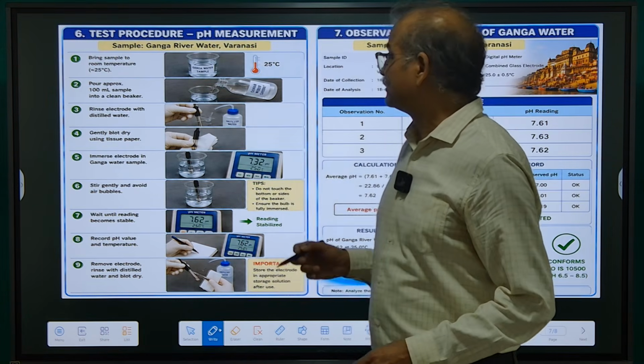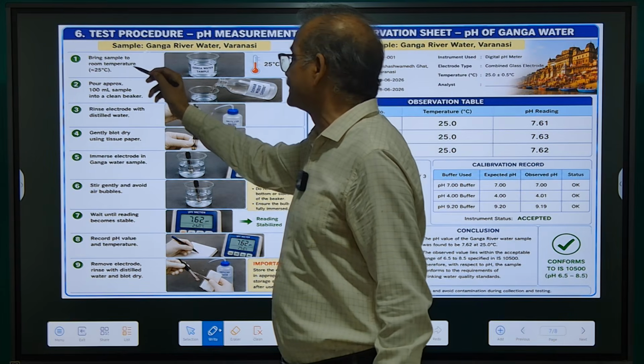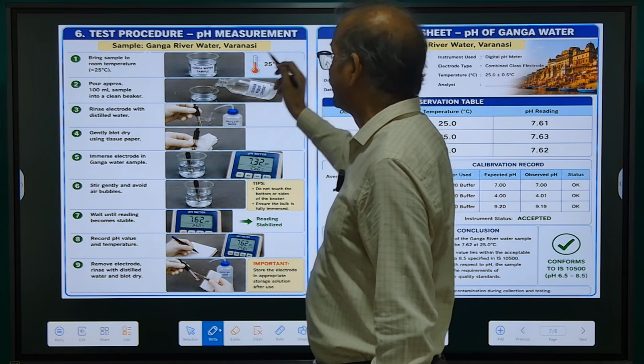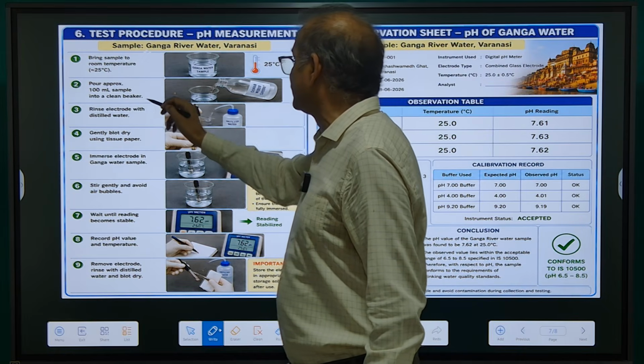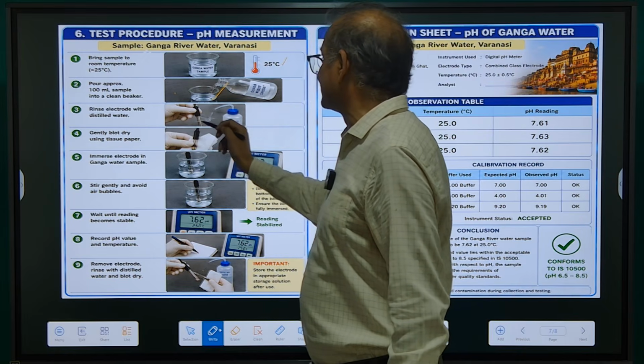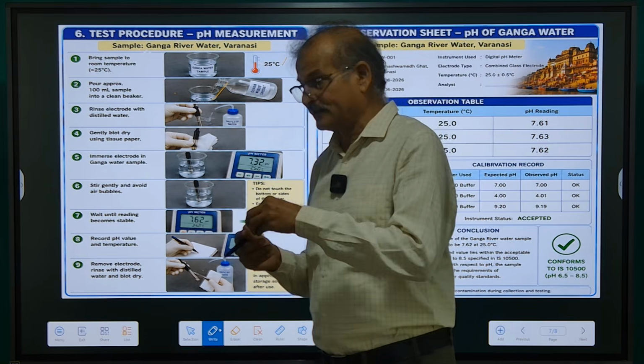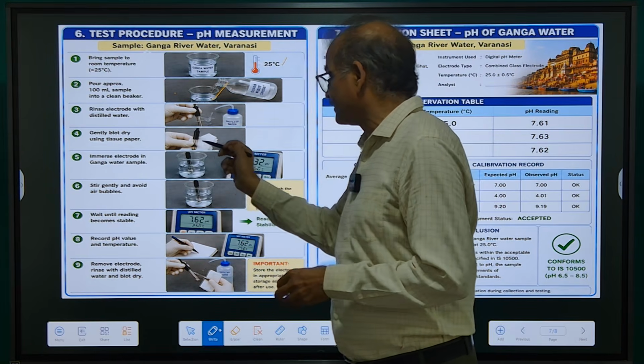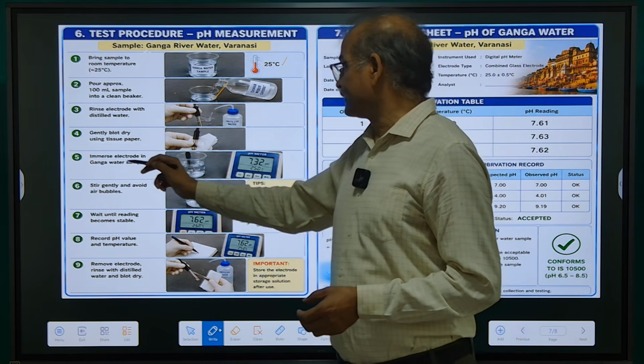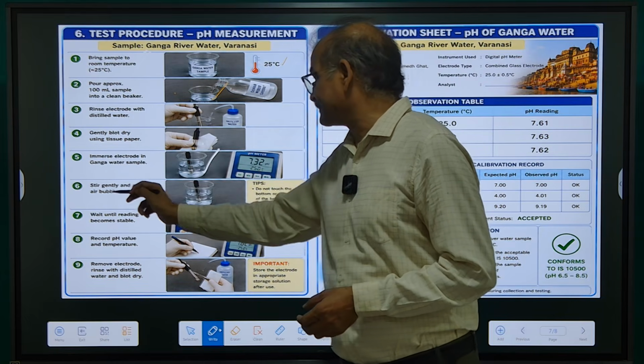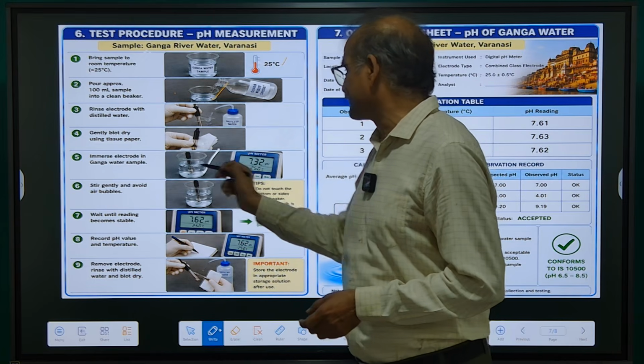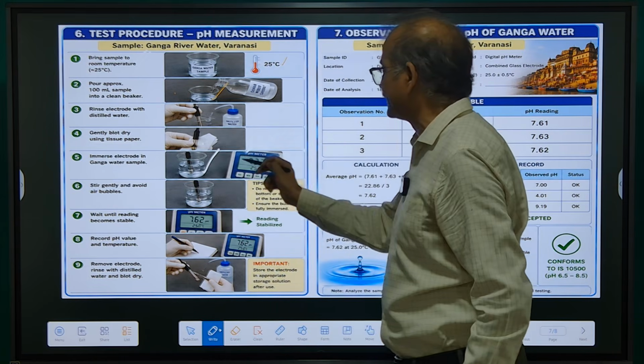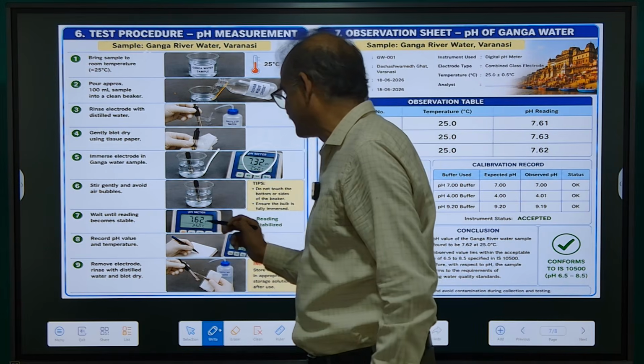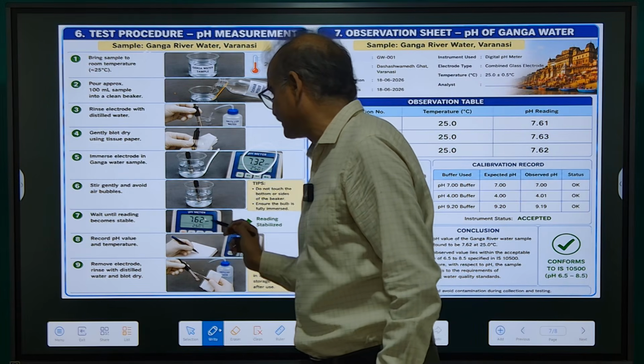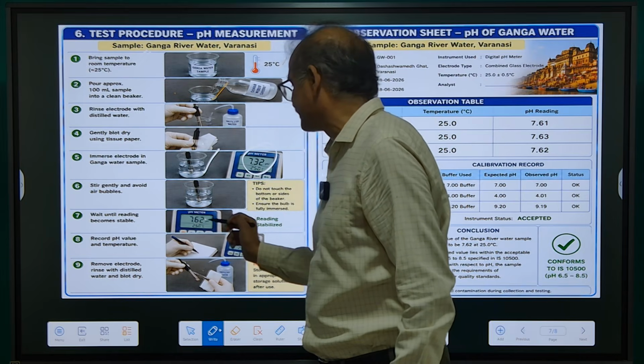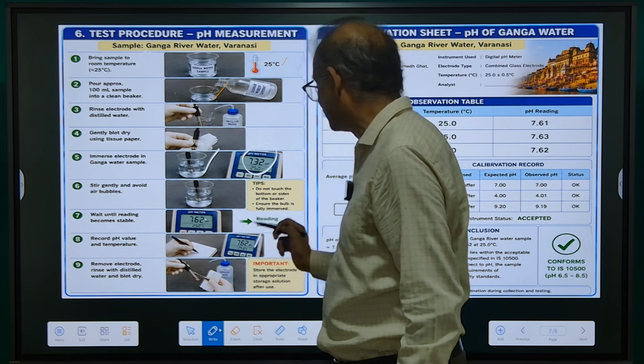For doing the test, bring the collected sample to room temperature, 25 degree centigrade or 27 degree centigrade, and pour approximately 100 ml sample into a clean beaker. Rinse the electrode with distilled water and gently blot it dry using tissue paper. Make it dry using tissue paper. Immerse the electrode in the sample. Stir gently to avoid air bubbles. When we first place the electrode, it has recorded 7.32. When we stir gently, it has increased to 7.62. Wait until the reading becomes stable at 7.62. Record the pH value 7.62 of the first solution.